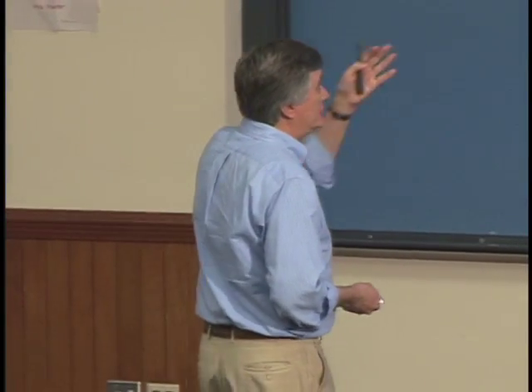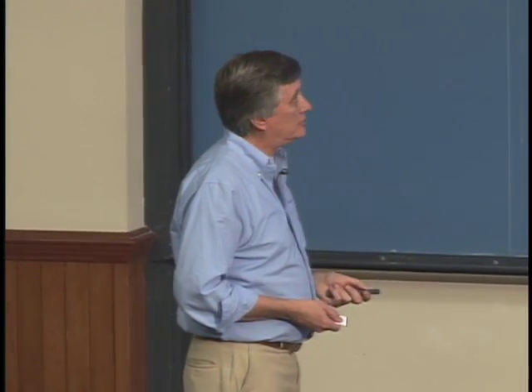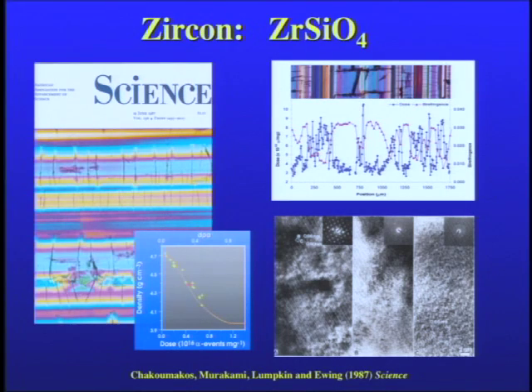Laboring away in obscurity, we began to work on things, and so zircon was a natural phase to work on. And the interesting approach was to study radiation damage. This is from a zoned zircon, and this is a traverse, and this is in cross polar, so you see the variations in birefringence. Well, as something becomes amorphous, the birefringence decreases, right? And so the lower the birefringence, it's hard to see in this, I'm sorry, the higher the dose. So actually across this few millimeters, I had the perfect radiation damage experiment.